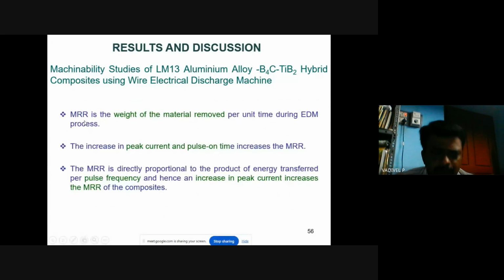The metal removal rate is the weight of metal removed per unit time during the EDM process. An increase in the peak current and pulse on time increases the metal removed. So when we increase the peak current and pulse on time, the metal removal rate is high. The metal removal rate is directly proportional to the product of energy transferred per pulse and frequency, and hence an increase in peak current increases the MRR of the composite.